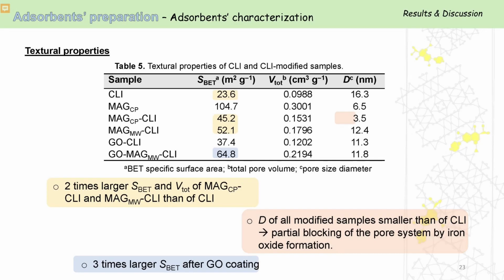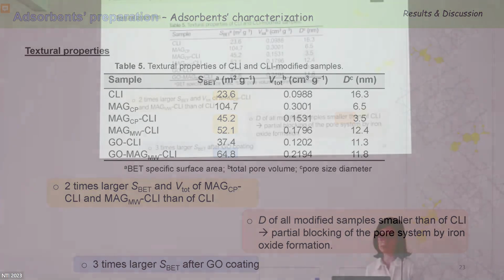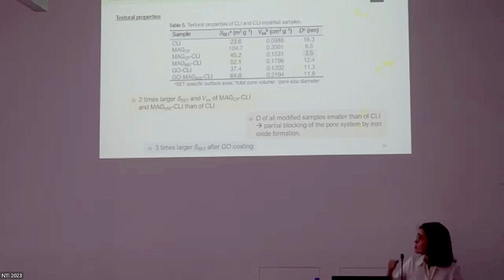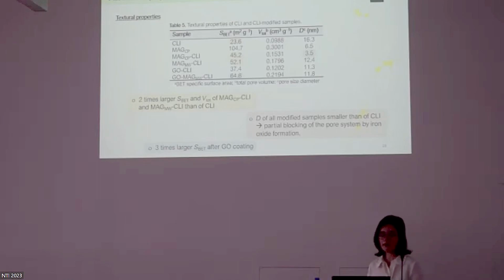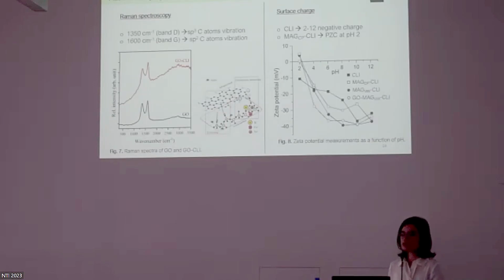The results of BET analysis showed that the specific surface area of clinoptilolite increased approximately 2 times after the modification with magnetic nanoparticles, as well as the total pore volume. On the other hand, the pore size diameter decreased for all modified samples. This can indicate the formation of a second layer of magnetite nanoparticles on the clinoptilolite surface and partial blocking of the pore system by iron oxide formation. But the synergetic effects of magnetite nanoparticles and graphene oxide led to an increase of the clinoptilolite surface area 3 times.